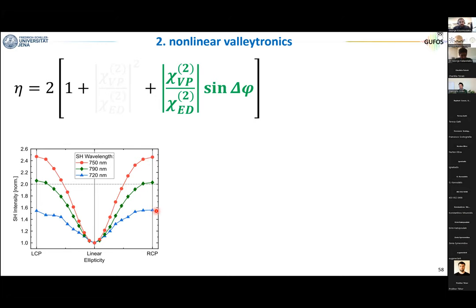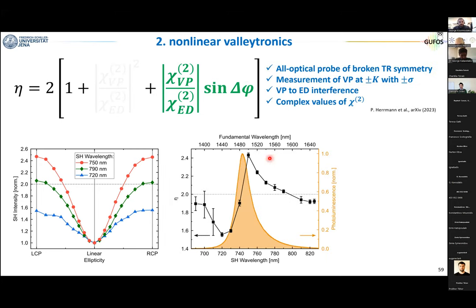And this is something that you can only explain if you consider the interference between the electric dipole and the valley polarization. And now let me tell you, if you do a scan of the wavelengths across the excitonic resonance in WSe2, the orange curve is the photoluminescence of our material, so exactly when we have the linear response, the absorption or the emission of the material, you see that the ratio, this eta, is never 2, and instead it has a shape that is very similar to the first derivative of the absorption. So it's very similar to the imaginary part of the linear refractive index of the intrinsic response of the material.